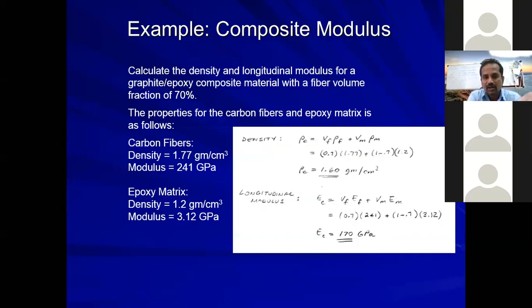So the next is the density of the composite, calculated from the given volume fraction of 0.7 and fiber density of 1.77, and the matrix volume fraction of 1 minus 0.7, with matrix density given as 1.2. Why 1 minus 0.7? It means 70% volume fraction of the fibers is used in this composite structure, so the remaining is matrix, which is 30%.